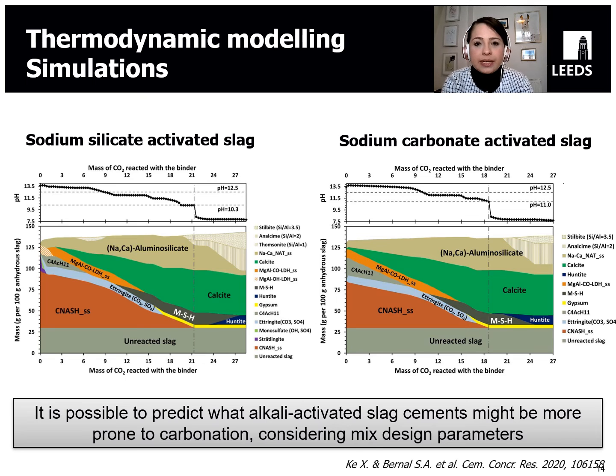So of critical importance, perhaps for people that are very interested in the correlation between carbonation and corrosion of steel rebars, is identifying how the changes in phase assemblage as carbonation progresses might influence how the pH is changing over time. So it's a two-thing situation. If we lose the binding phases in our material, the strength-giving phases, but the pH is still high, it is kind of irrelevant up to a certain extent. So what we're looking for is to conserve the majority of our strength-giving phases before we reach a pH that could destabilize any oxide film that can form on a steel rebar here.